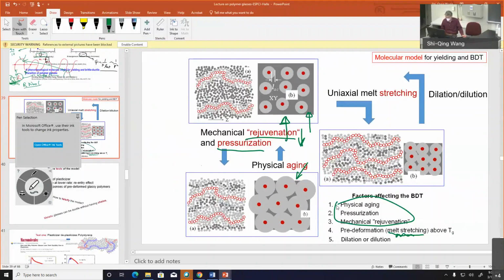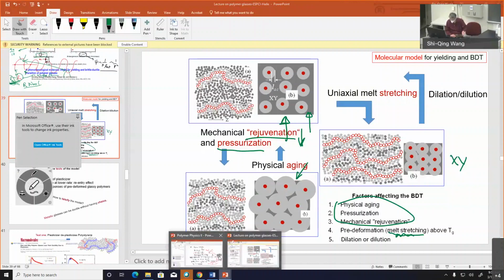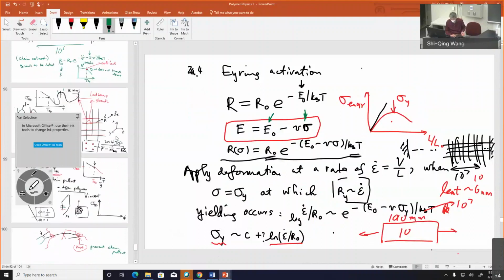And the rest is also very straightforward. Melt stretching brings the network in the XY direction, you're drawing in the Z direction, much closer. By definition, because when you melt stretch, your cross-sectional area shrinks. So in the fine deformation limit, all the backbone collapses into a smaller cross-sectional area. And therefore, your job to activate becomes easier. And dilation has exactly the opposite effect. So that completes the whole discussion on the latest understanding at the chain level that speaks about why polymer can yield and how a brittle-ductile transition arises.